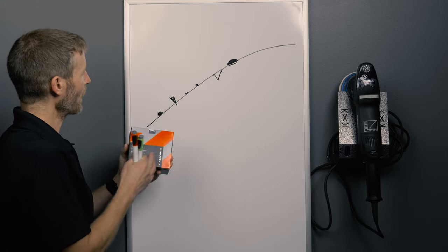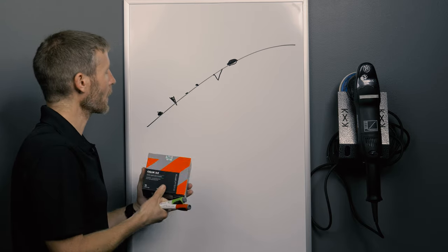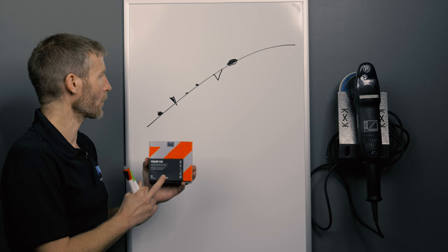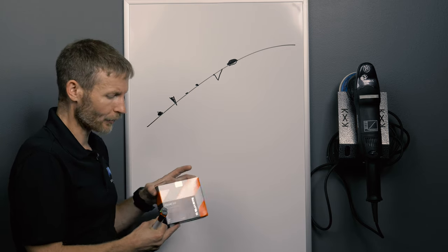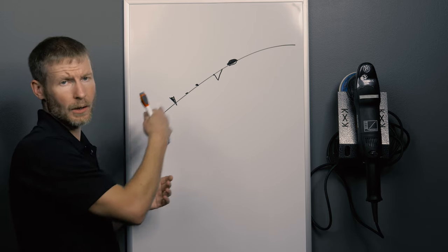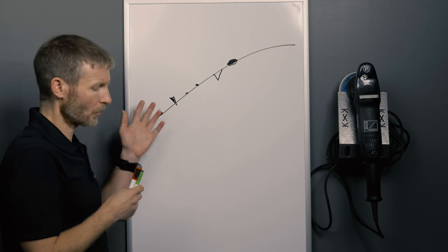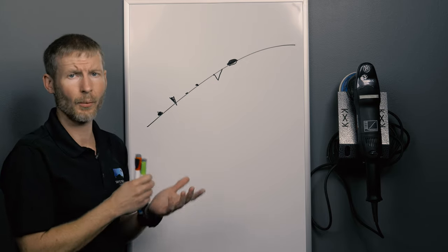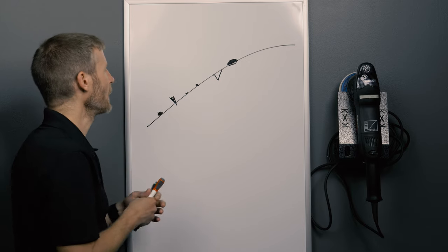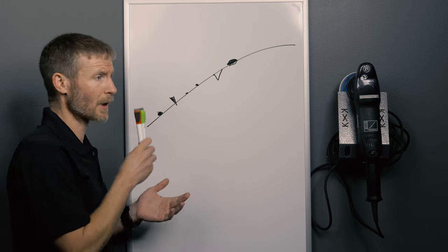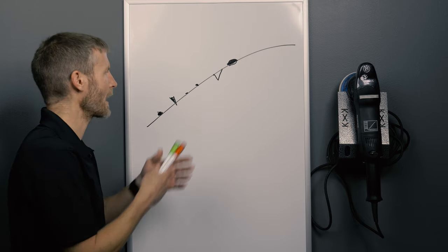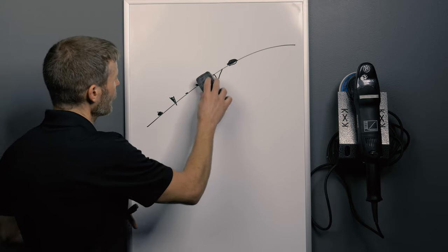So you don't want to go and try to put this on top of that. Not only will you have this on top of that and not have applied it correctly, but you will also not be able to allow this to bond to the paint because a ceramic coating, unlike a wax, requires a 100% surgically clean surface. And just cleaning it alone won't necessarily make it to where the ceramic coating can bond to it, just because you can't be 100% sure you got everything. So you want to start with cleaning it chemically, but then you're going to come into the mechanical cleansing portion, which requires polishing compounds and abrasives.